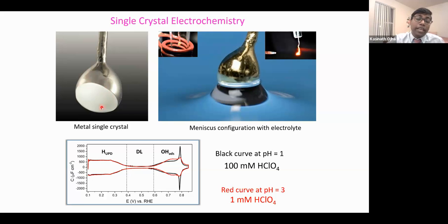When we cut those orientations, those particular sites, we use a laser and reflection method to get the accuracy of that surface. So if our accuracy goes to 0.001 degree in angle, that's basically a bit deviated from the surface, but we maintain the angle when we cut those surfaces, and that is very important.